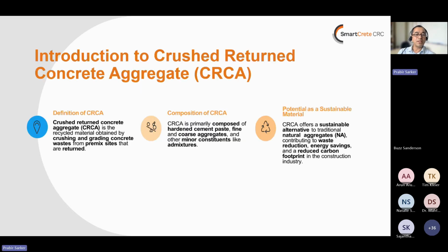So, crushed return concrete aggregate. Vinod has already presented that, so I will not spend much time on it. But the difference between crushed return concrete aggregate and conventional C&D waste aggregate is that this CRCA is a very pure material. It doesn't have any impurity like brick, or timber or tiles, glass, plastic, that we can find in C&D waste aggregate. So it's a very pure material.